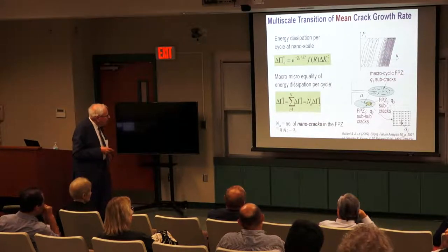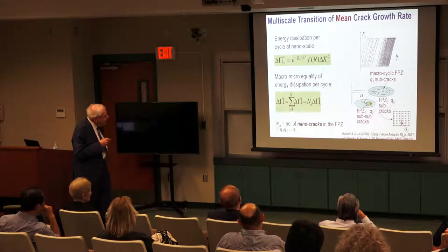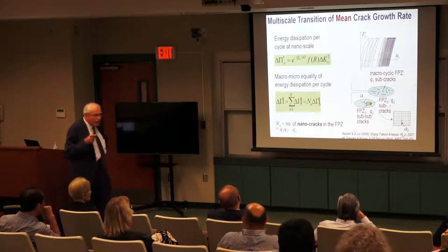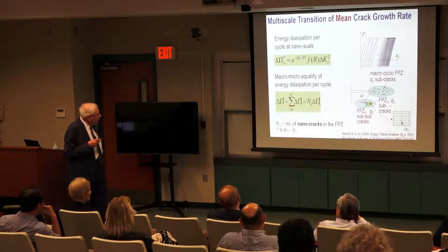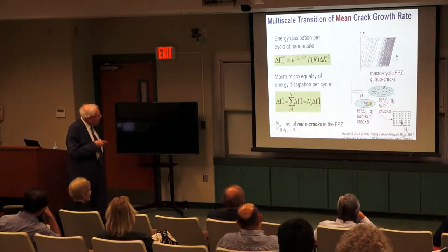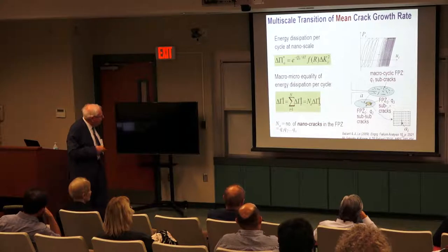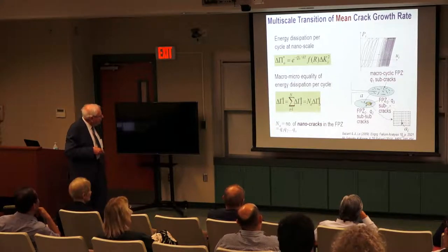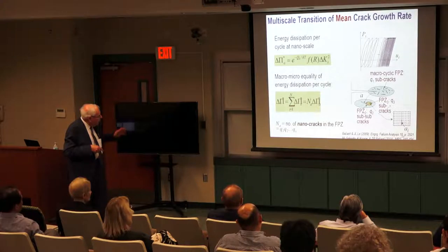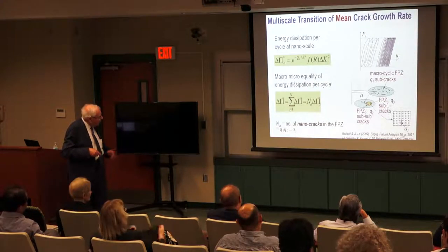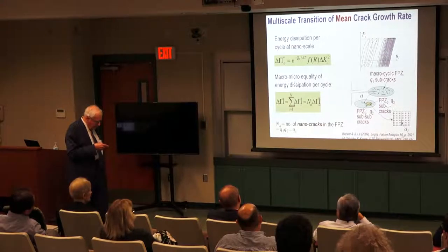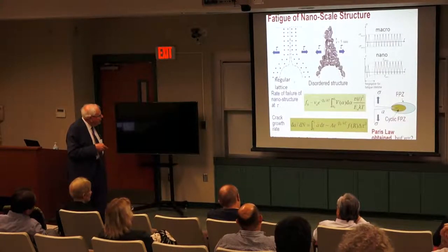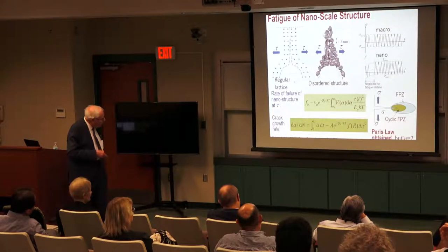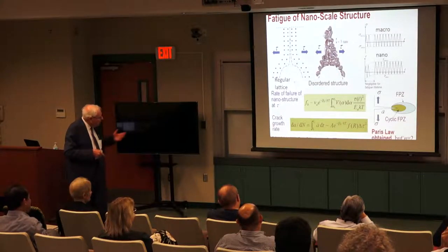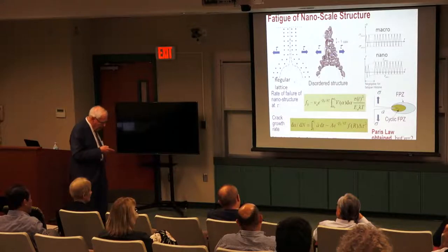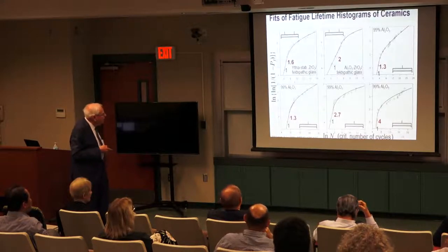It's impossible to calculate exactly, but we can argue about the tails again simply. But here we must argue a different way. It's subcritical. So it's not a question of failure, it's a question of dissipating the same amount of energy per unit advance of the crack or per unit cycle on the macro and micro. And if you impose this condition, energy dissipated on macro and micro, you conclude again that the tail is growing. And you get from this distribution a higher exponent for concrete, about 10. Same kind of behavior. And then you can calculate lifetime.